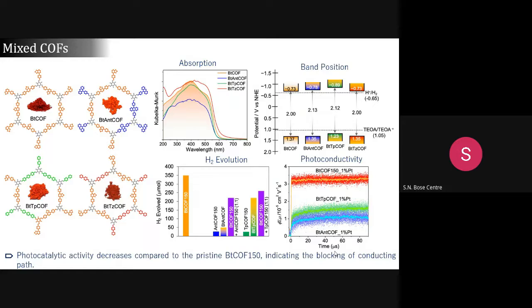Now, why is it less? Because the charge transport happens in this direction or in the in-plane direction. We don't know which direction it is happening. But the other material acts as an impurity in this case. This kind of unit acts as an impurity and just stops the percolation path for the electrons or holes to travel to the active center of the catalysis. So that is why BtCOF150 is the best among the others. From all these experiments, what we conclude is that porosity is of course an important factor.